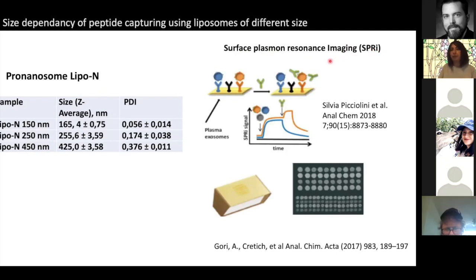That means that it's a kind of a mixture between a microarray, but with a surface plasmon resonance detector that can detect the accumulation of mass on each spot of a microarray, that can monitor online the accumulation of mass on each spot. And we are lucky because we have in place a collaboration with a group in Milano from Fondazione Don Carlo Gnocchi, and I thank Silvia Picciolini for running these experiments. They published in Analytical Chemistry in 2018 a paper on the surface plasmon resonance detection of EVs on an antibody microarray spotted on the SPR chips, these gold chips that you might have seen before.